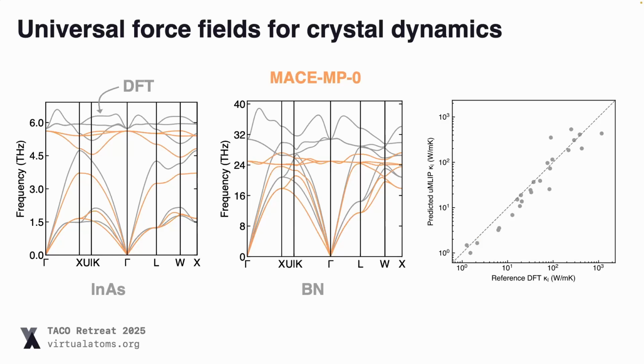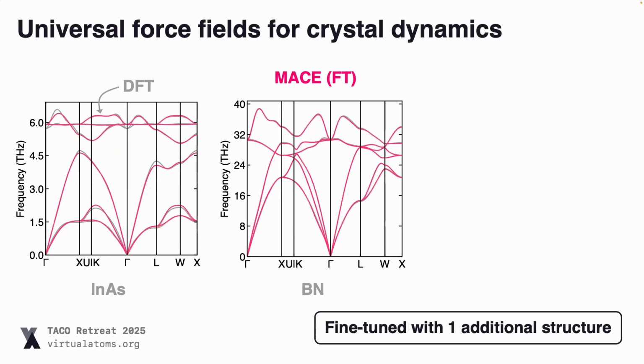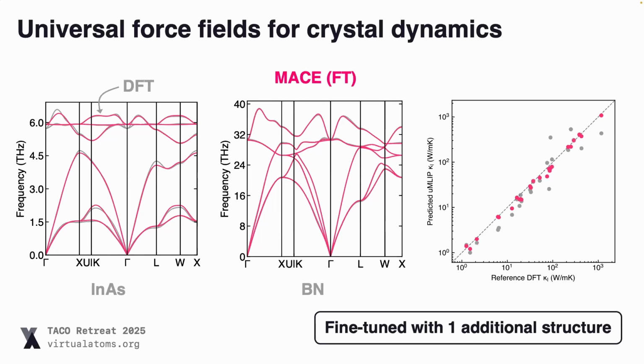What we've recently shown is that just by taking one structure calculated with DFT with just some random displacements, you can use one of your hiPhive structures, for example. Fine-tuning on a single structure, you can get rid of all of those discrepancies, get very nice agreement to DFT, and also if we do this for a bunch of materials, we can get very nice agreement on the lattice thermal conductivity as well. So I think by combining these machine-learned force fields and the hiPhive approach, it could be a very quick way to get lattice thermal conductivity.